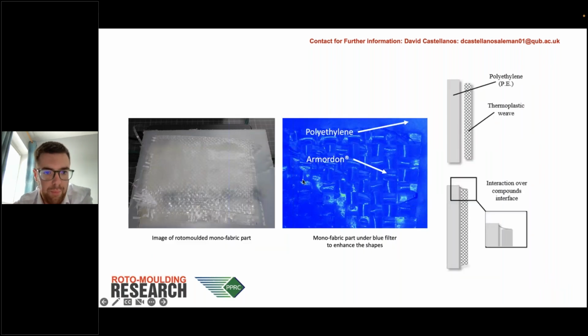And he then placed them manually into a rotationally molded polymer melt by opening the mold during the molding cycle. So he reversed it out of the oven, took the mold apart and placed this fiber into the polymer melt and then returned it back into the oven. You can see though that there's sort of variable results with doing that because of the manual placement, and in some cases, if it doesn't fully get embedded within the polyethylene in this case, and then other areas can end up being deeper. So it's not a very controllable process.